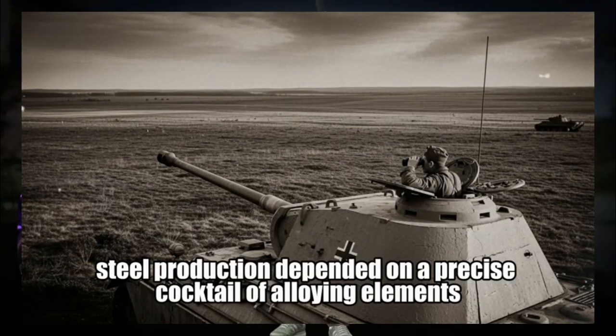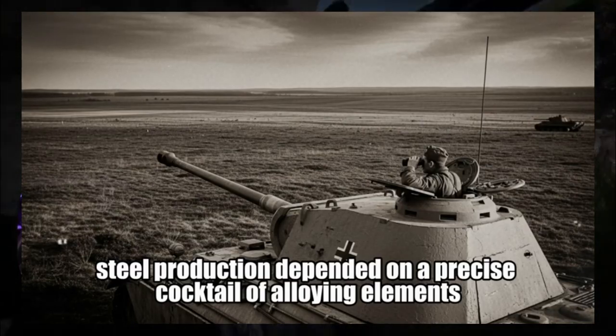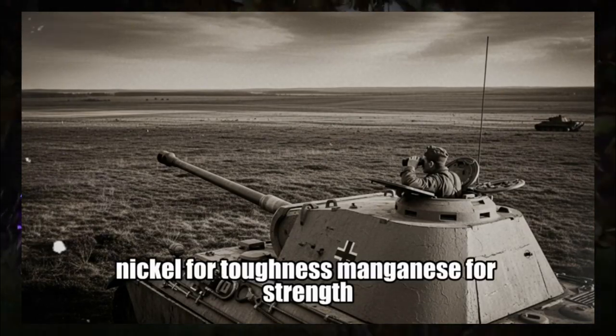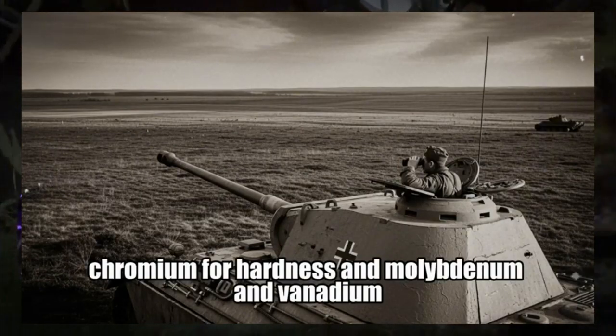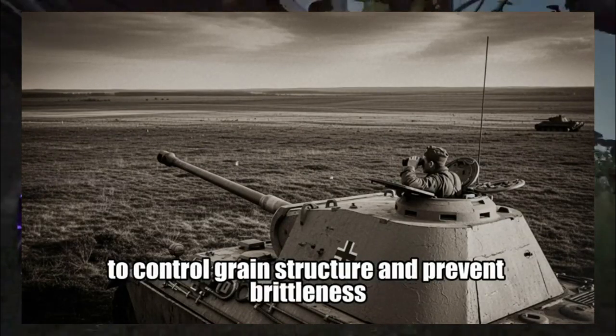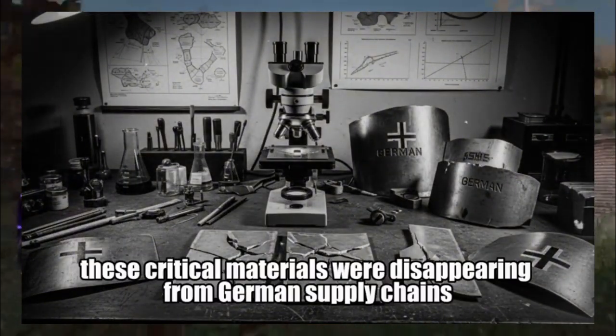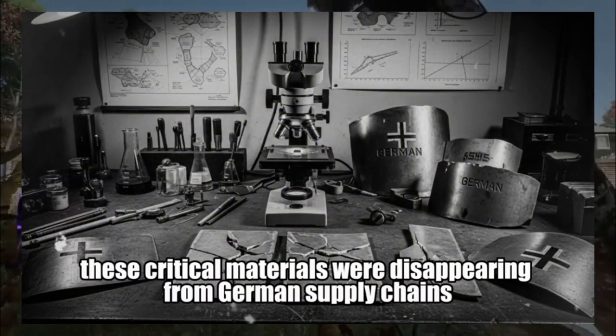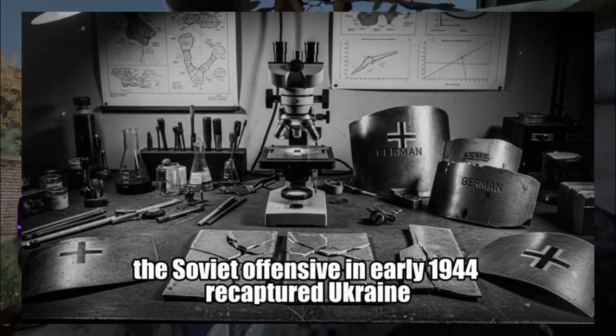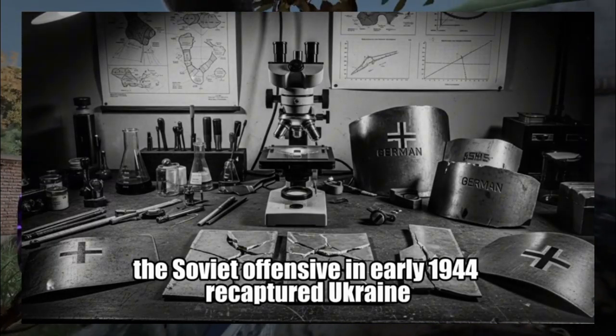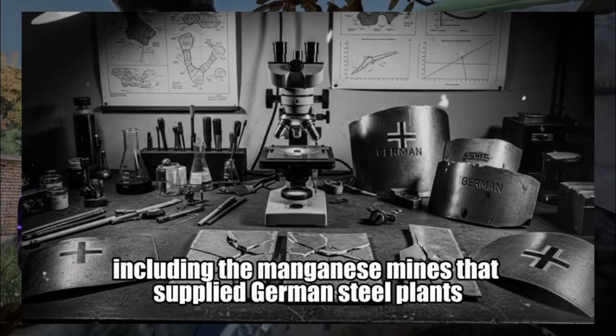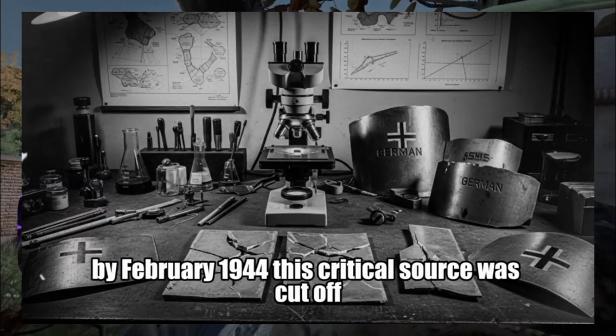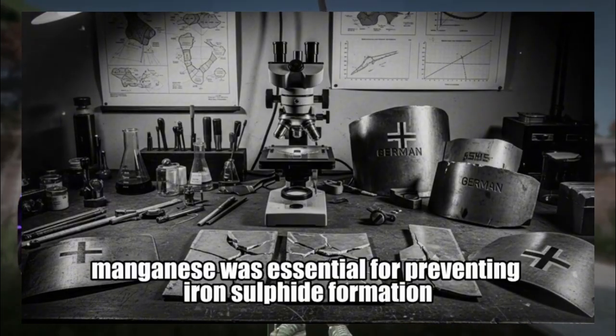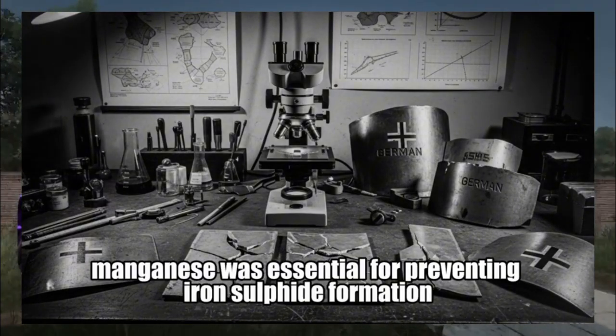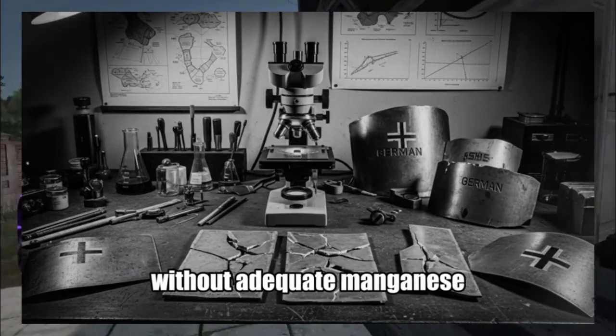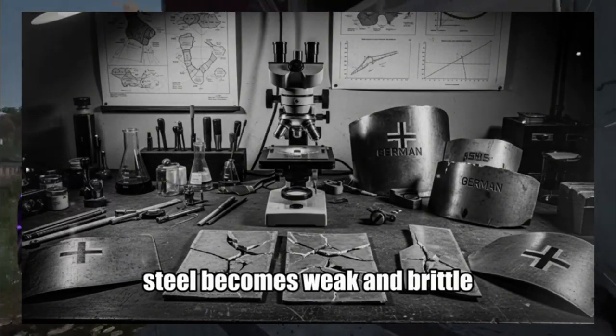Germany's armor steel production depended on a precise cocktail of alloying elements: nickel for toughness, manganese for strength, chromium for hardness, and molybdenum and vanadium to control grain structure and prevent brittleness. As early as 1943, these critical materials were disappearing from German supply chains. The Soviet offensive in early 1944 recaptured Ukraine, including the manganese mines that supplied German steel plants. By February 1944, this critical source was cut off. Manganese was essential for preventing iron sulfide formation and increasing hardenability. Without adequate manganese, steel becomes weak and brittle.